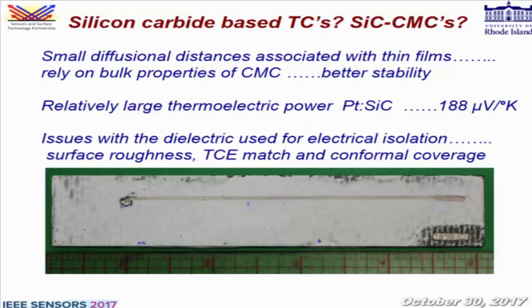So I'm going to start off with temperature sensors, thermocouples. Most of the work that we've done in the past was with thin film thermocouples, platinum palladium as an example. At high temperatures, we had a lot of issues with these, such as dewetting of the thin films, diffusion, small diffusional distances, and selective oxidation of the palladium films.